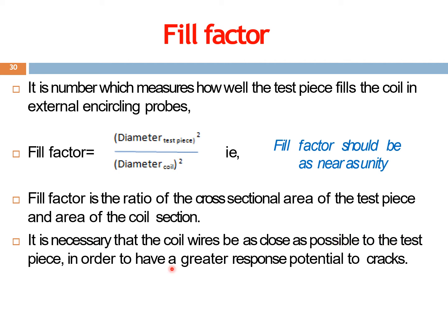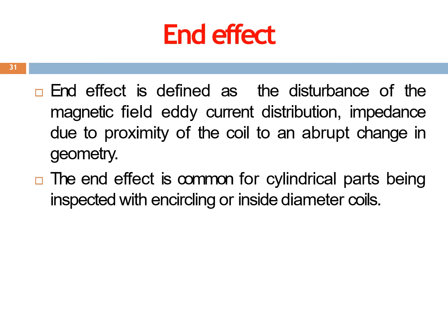That is, we discussed previously, right? We have discussed previously about the lift off effect. So this is equivalent to a fill factor. The lift off height should be as minimum as possible, and the fill factor should be close to unity. So the condition is satisfied when the coil wire is as close towards the test piece, we get better response to cracks, the lift off distance is reduced, and the fill factor will reach the value unity. So this is the condition for fill factor. This factor clearly affects the performance of eddy current testing.